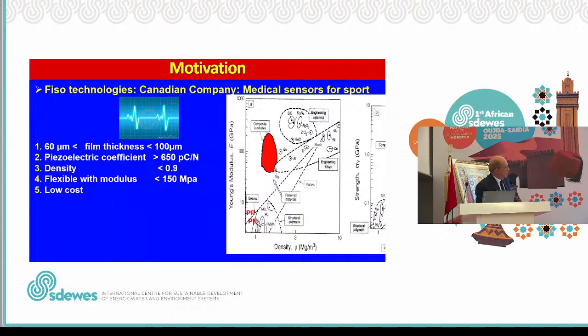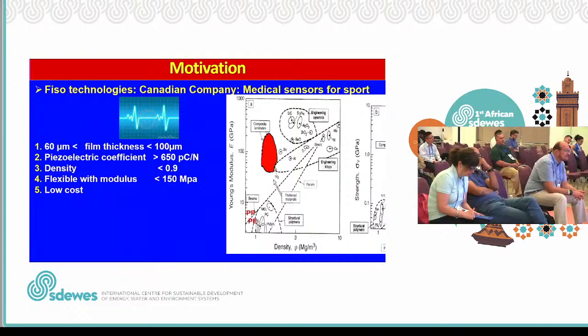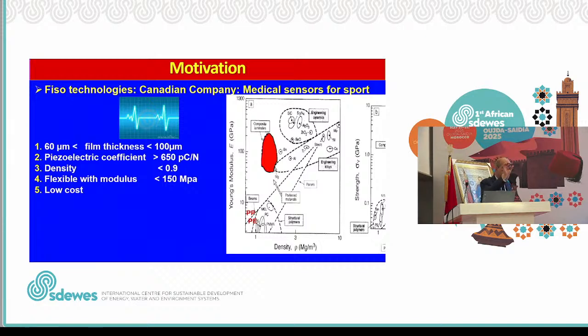So if you look at all the materials, on the y-axis you have what we call the Young modulus, that measures the toughness and the stiffness of the material, and on the x-axis you have the density. The majority of piezoelectric materials are ceramics. See, there is a circle of ceramics. They have a very high modulus of a few hundreds of gigapascal. This is not what we want. We want something in megapascal, not in gigapascal. The density is very high. We are targeting a density below 0.9.